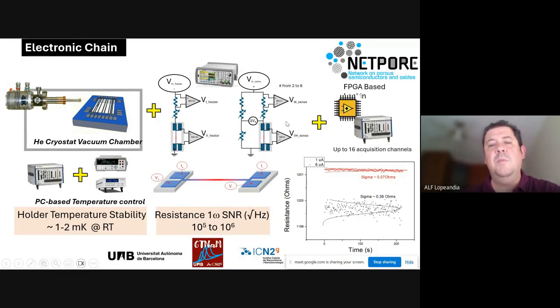The fact is we could measure the temperatures in both cases. The holder temperature stability, as I said, is around 1 millikelvin, and we can see here the resolution. If we do not have a correct oscillation, as you can see here, the drift of this resistance is because of the temperature of the holder, not because of the resolution of the 1 omega signature. In order to be able to measure up to 4 channels in parallel, we have developed an FPGA-based lock-in amplifier that can be easily scaled up, in order to have several measurements in parallel.